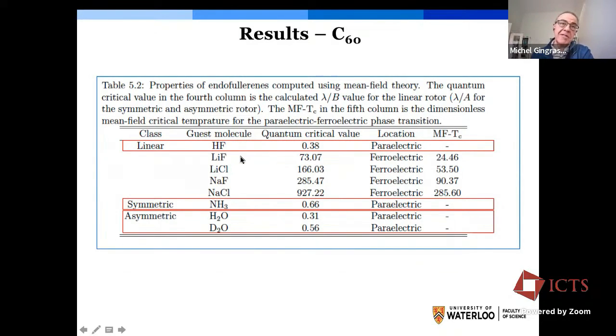Tentatively, this is consistent with what has been seen experimentally for HF and H2O, where no spontaneous formation of a ferroelectric has been found. The density functional theory calculations suggest that it should be possible to insert lithium chloride, sodium fluoride, and sodium chloride in C60 molecules, but that has not been done thus far. And one will have to see whether or not those molecules are actually sufficiently small that they can be inserted into C60 cages without destroying the cage or distorting it too much.